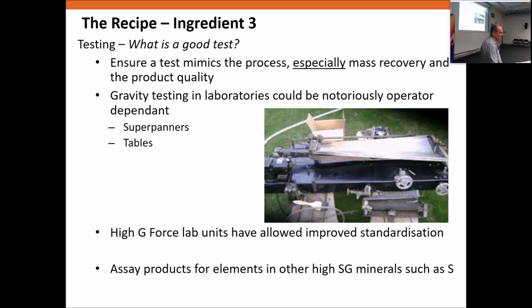I must put a plug in for the little Falcon and Knelson lab units these days. They're a lot simpler, a lot less variables, and they have improved standardisation. For example, Andre Laplante's gravity recoverable gold test. And it's rare to see, but a knowledgeable lab will also assay for other things, as I alluded to before, to give information on what the process is doing. For example, if the recovery of sulphur is the same or higher than the recovery of gold, then the gold is just likely along as a passenger, and the gravity process is actually recovering the sulphides.